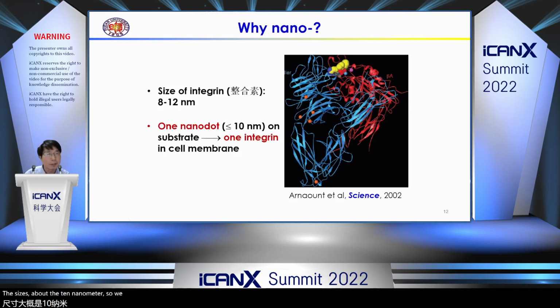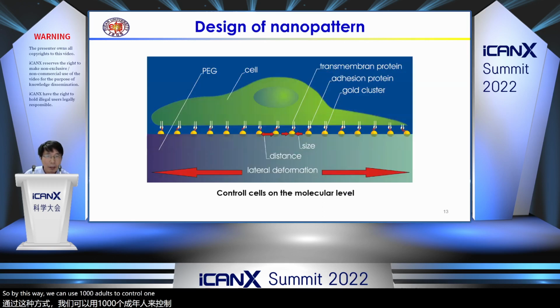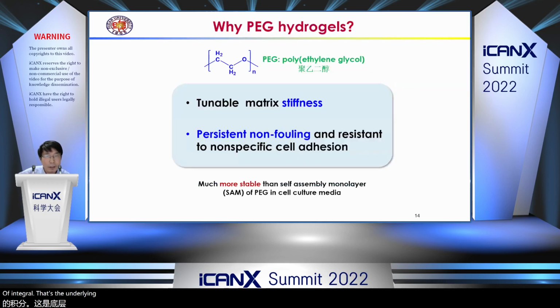So we hypothesize that if we fix one nanodot, also about 10 nanometers, on the solid substrate and link RGD, and then we culture cells on the substrate, the RGD can spontaneously bioconjugate with integrin. In this way, we can use one nanodot to control one integrin. So we can use the nanodot array to control the spatial distribution of integrin. That's the underlying science. Then, why PEG hydrogel?